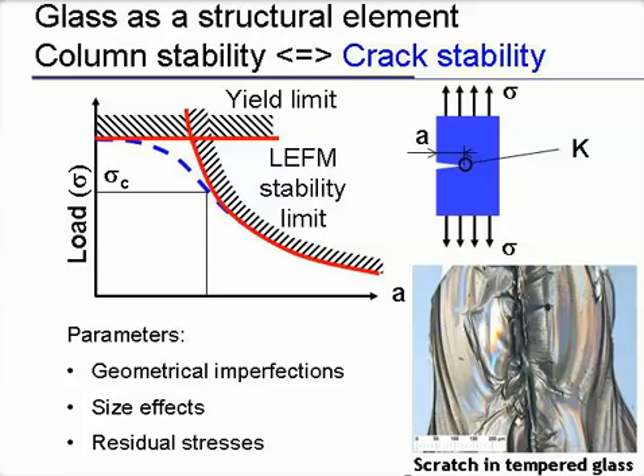And now, again, you have the different cases, the scratch. And now the difference is that in this case, the limit is not in function of the stress. Now it's a function of a new parameter, which is the stress intensity factor. But again, you have influence of geometrical imperfection, size effects, and residual stresses.